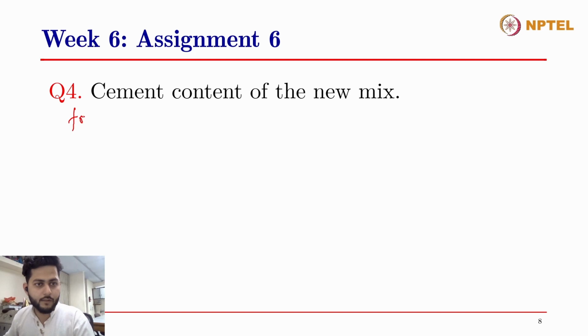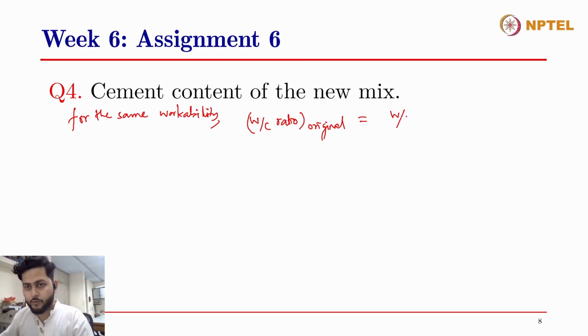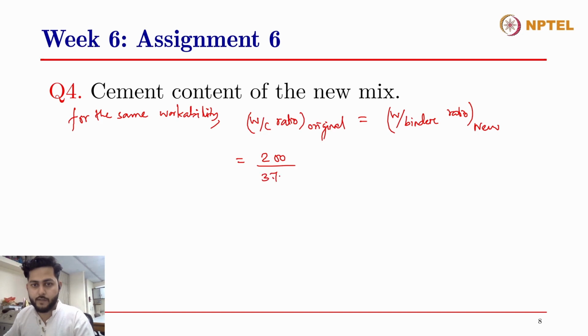So for the same workability, the original water to cement ratio can be equated with the water to binder ratio in the new mix, right? So that will be 200 divided by 378 equals water dash, which is the new water content, divided by C dash, which is the new cement content, plus K times F dash, right?